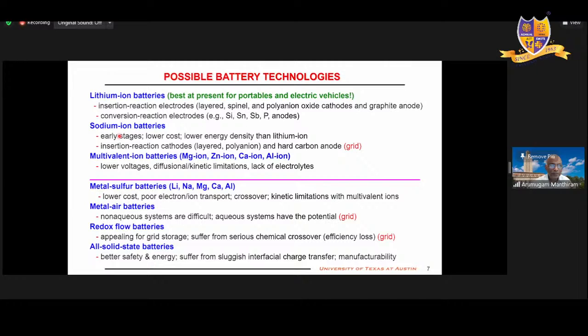Right now, the lithium ion energy density is 250 watt-hour per kilogram. Like I said, in the sulfur, if you throw a lot of liquid electrolyte or a lot of carbon, this number can go to 50 watt-hour per kilogram, for example. That is not good. So when you increase the nickel content, that number can go to 300 or 350. Instead of graphite anode, if you have lithium metal anode, that can go to 400 or 450. If you go to sulfur, maybe 500 watt-hour per kilogram, doubled. And then if you go to sodium, all these numbers will be approximately 50 less than the numbers you see here, analogous to that.